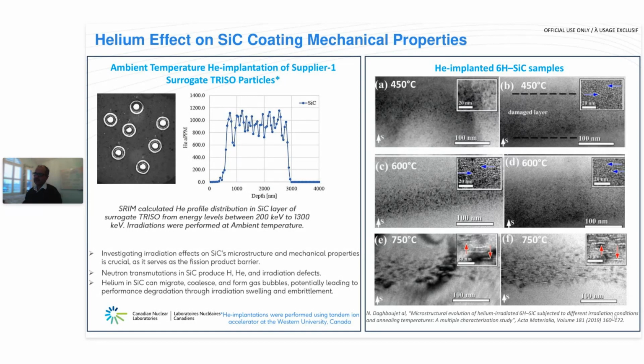So to start, we did some helium implantation in the surrogate TRISO particles, in the silicon carbide coating from supplier one, using an ion accelerator at Western University in Canada. We used a multi-energy beam from 200 keV to 1300 keV to perform the helium implantation at room temperature. In the left box, top right image, there is a helium profile distribution in the silicon carbide layer, where from about 1 micron to about 3 microns, there was about 1000 appm level of helium.